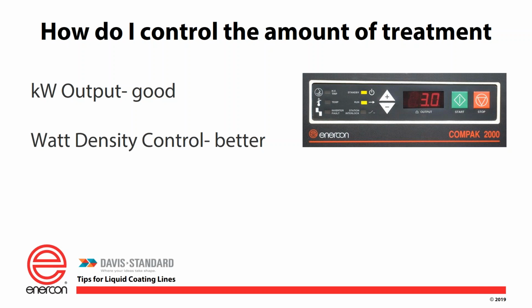The web gets into the treater, it's running at a lower speed, gets a lot of dwell time, a lot of power, and now the web starts doing odd things. You know, it can pucker, it can wrinkle, it can get a big static buildup, things of this nature. And then when the web exits the treater, then more problems happen. The coating doesn't look right, it doesn't wet properly, maybe it's got sort of an orange peel look or something. You know, something in that process is not working.